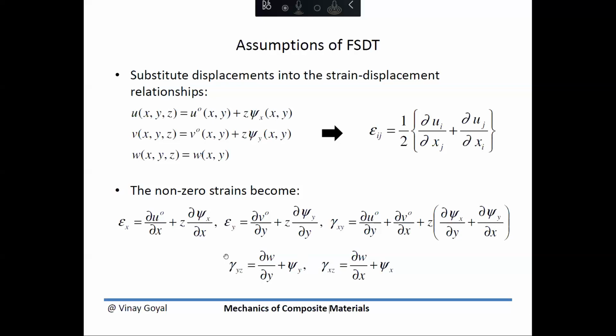And these transverse shear strains correspond also to the angle change in that plane if you were to initially start with a square. The angle change of that square corresponds to this shear strain. Notice how we can quickly recover classical plate theory by setting gamma to 0 and then solving for psi_y and psi_x, and then plugging it back here into this equation. Then I get 3 strains, and I'll get exactly what I got for classical plate theory.